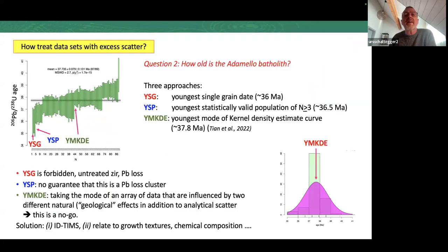Then, how old is the Adamello batholith? There are three approaches. The youngest single grain date is absolutely forbidden. This is 100% sure lead loss. The youngest statistically valid population of at least 3. This is kind of the agreed procedure in detrital zircon. I think in this case, I would be very careful. I would assume this is still biased by a lot of lead loss.